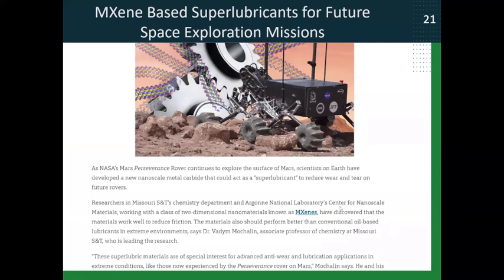And actually, when we published this work, it was around the time when the Perseverance rover landed on Mars. I thought that this is a perfect example where you can use these properties of MXene as a superlubricant, because when you are in space, you don't have water and you don't have oxygen in that environment. So this is exactly an environment which is good for MXene to demonstrate superlubricity. Even on Mars, you don't have much oxygen and not much water to degrade it. So this may be one of the best materials for lubrication in space, where many other lubricants fail.